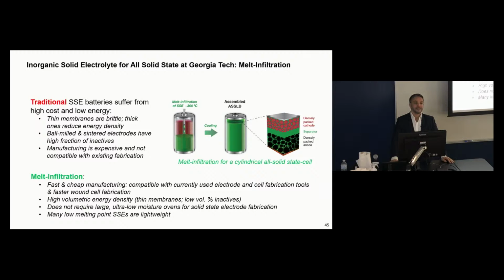And it's still unclear if this technology is ever going to be useful because ceramic electrolytes are much heavier and they're much more difficult to process, right? So if you want to make all ceramic batteries, you have to have all ceramic electrodes. You have to sinter them at high temperatures, which is expensive, right? You have to use very different processes, completely incompatible, or partially at least incompatible with all production of lithium-ion batteries worldwide. And people already build in factories. They committed tens of billions of dollars, if not hundreds of billions of dollars, to build all these gigafactories around the globe, right? And if technology is not compatible with these factories, it's a huge problem for deployment.